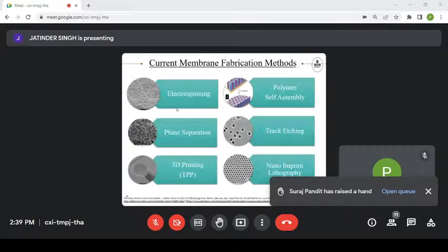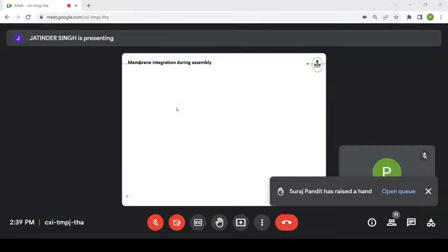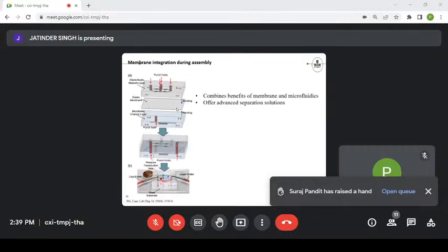There's a lot of normal membrane fabrication methods as well that you can just buy off the shelf, just like the dialysis membranes. And we can use those membranes in microfluidics as well, simply by making them part of the microfabrication process. So we make the fluidic structure, put the membrane in place, we bond it. In this way, this is an elastic membrane. So you can do that with porous membrane. Any membrane that you can get off the shelf, you can actually make part of your microfluidic sandwich as well.